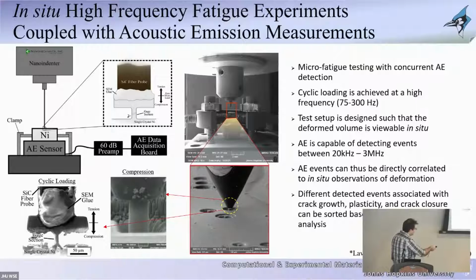You can fabricate specimens inside a bulk sample. So this is like a millimeter thick substrate of any material you're interested in. You fabricate these type of pillars in them. They can have pillar geometries. They can have dog bone type of geometries, depending on what you're actually trying to answer or type of experiment that you're interested in. And then you can do these experiments in compression or cyclic loading or in tension and so on and so forth.